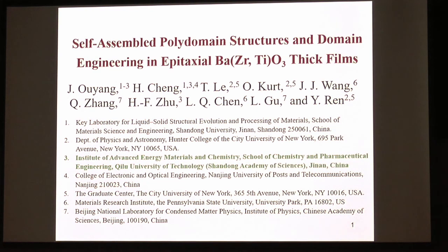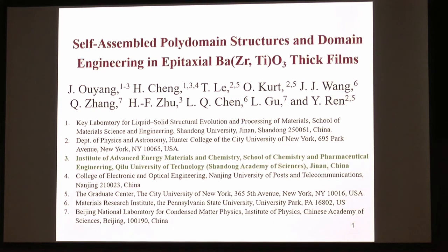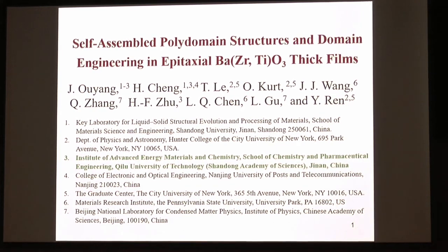Okay, one last question, and I think we should move. So I'm wondering if we care about the overall switching time or overall switching speed. Do these jerky events play a dominant role, or are they more like a minor effect? Well, if you're in this intermediate regime for strontium titanate, it's 100%. It's all jerky. If you go into field-driven barium titanate, it's also all jerky. So it's not the question of whether the jerky is dominant or not in most materials. In most materials, it is jerky.